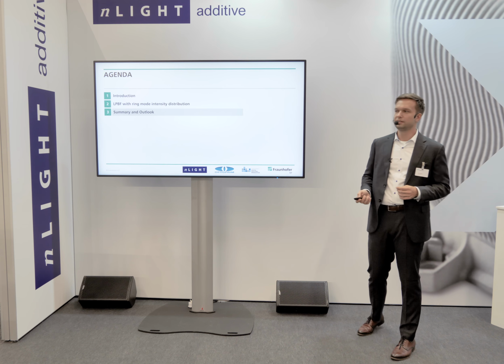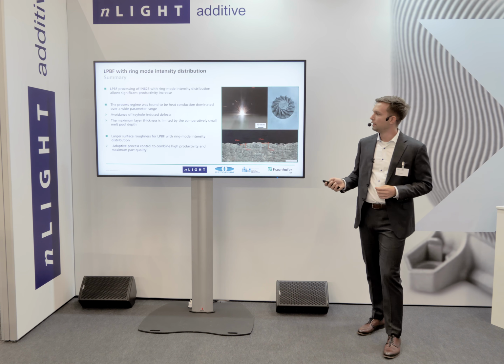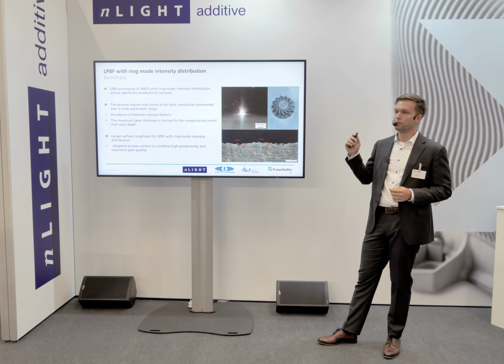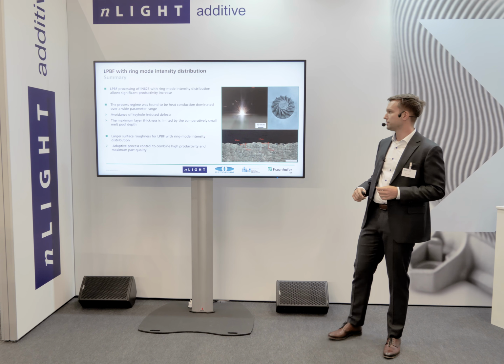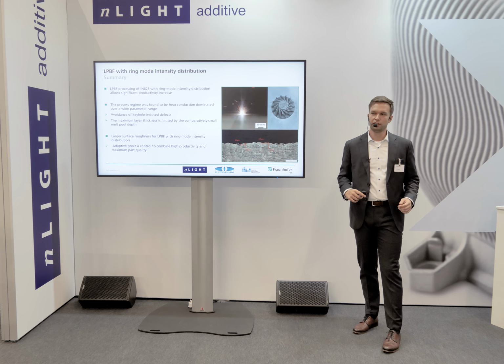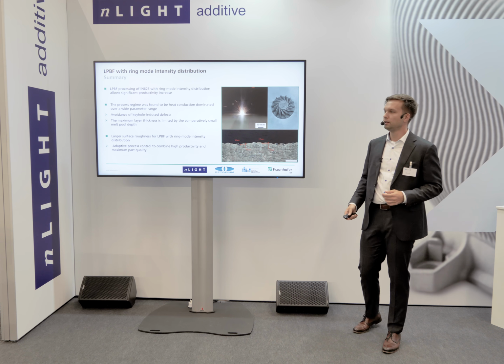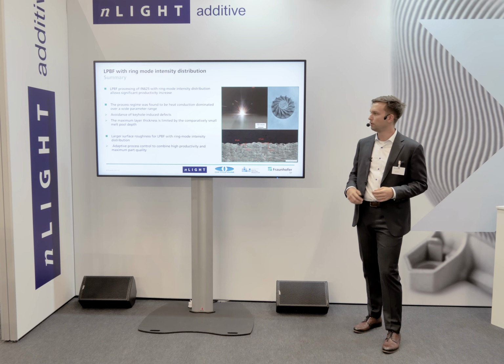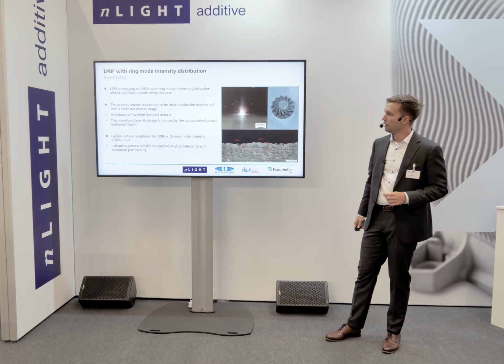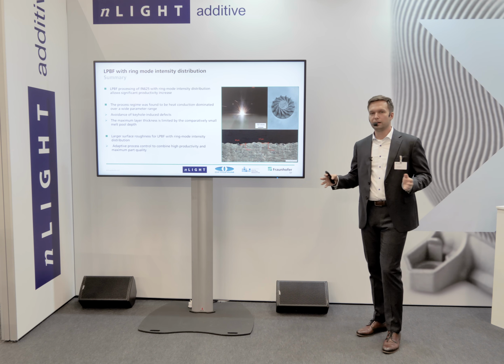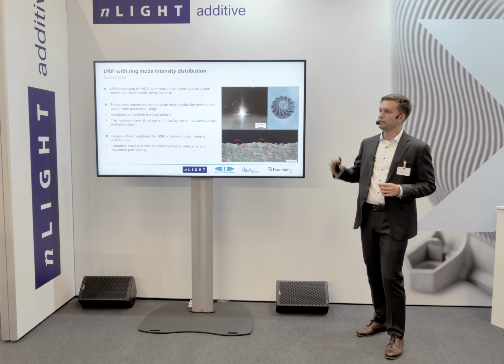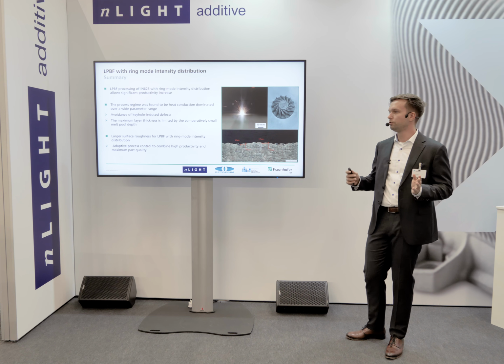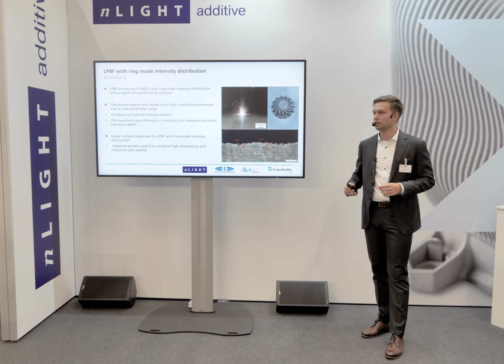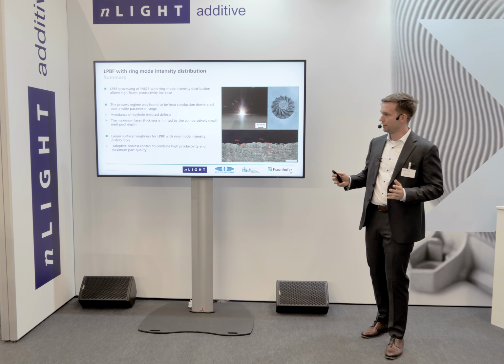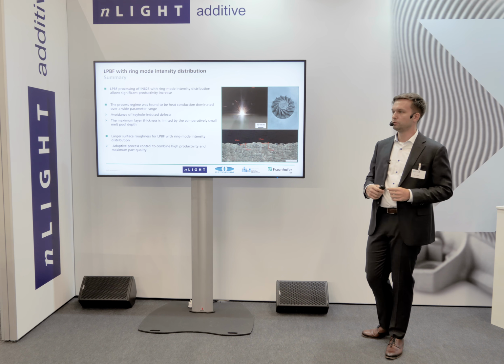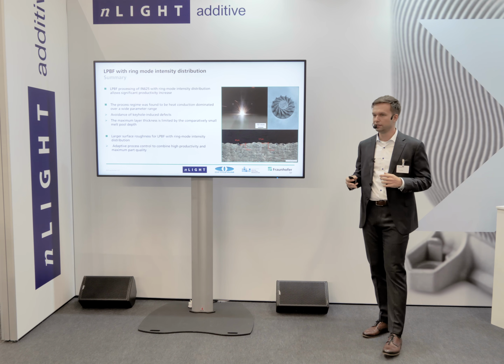Yeah, and this already brings us to my summary and outlook. So, as I mentioned, we were able to find very productive processing parameters for Inconel 625, which allowed us to scale the productivity by a factor of 2.5 compared to our reference, which is single mode Gaussian. The processing regime over the entire process parameter range was found to be heat conduction dominated, no risk of keyhole formation whatsoever. The melt pools are nice and flat, rather wide compared to our Gaussian reference, even when considering the defocused Gaussian.